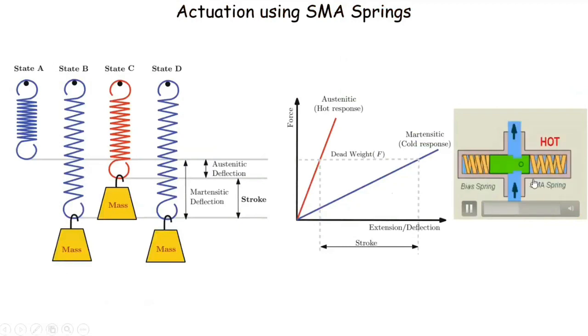So I will take that a little forward and say that this works on its own vertically. This actuator here, as I said, needs to be reset for cycling again. So you have this shape memory spring here, and an elastic spring which will press this fellow, and if it becomes hot, that will undergo the reverse transformation and push back, and in this case it's opening a valve. Maybe autonomously it is sensing the temperature and opening. Whenever it's hot, it opens a valve and lets the fluid pass. Now you can think of it as a passive smart material. Why? Because it is sensing the temperature on its own. You don't need a thermocouple or something. And then it actuates. So it can sense and actuate. It's a passive smart material on its own.